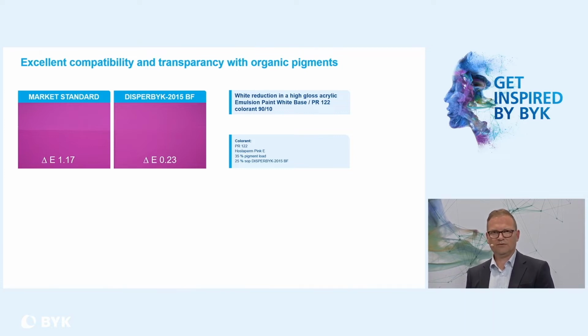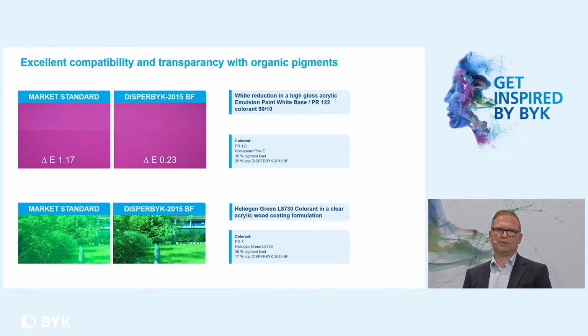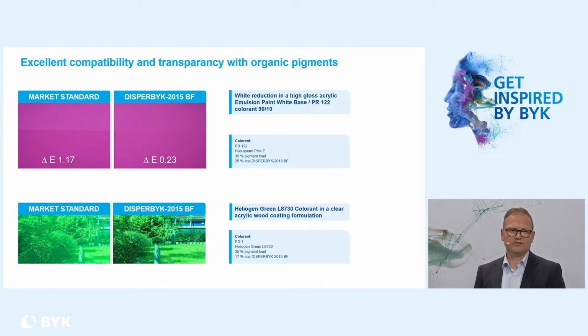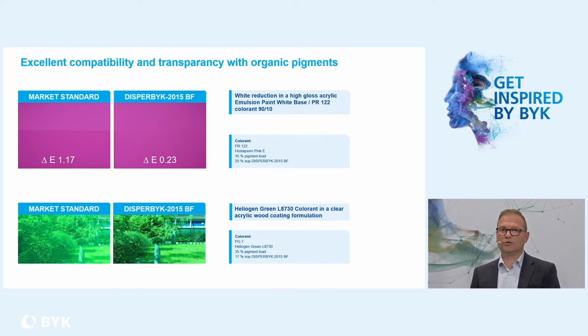But for wood coatings, transparency is very important. And here you see the second example. With organic green, with Heliogen Green pigment, we prepared the pigment concentrate and added it to a clear acrylic wood coating formulation. And most important, and you see it here, the very high transparency, the high clearness, and the nice color in the base paint.